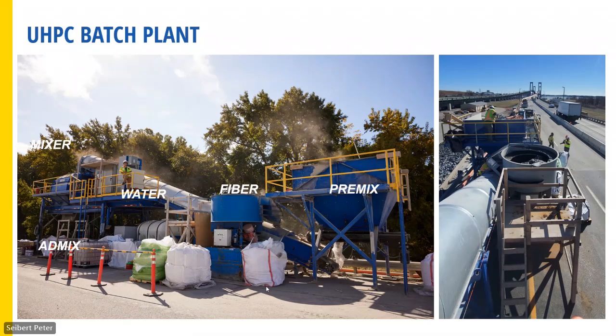You can kind of see quickly here, there's a big hopper. We would load all the pre-mix in there. And then as the mixer, which is all the way over to the left side, would be empty, the premix would dump out onto the conveyor belt and run up the conveyor into the mixer. At the same time, the computer starts telling the water pumps to turn on and the admixture to go in. And after we get the UHPC starting to blend up nicely, then this fiber doser here in the middle will turn on and put the fiber up the conveyor as well.